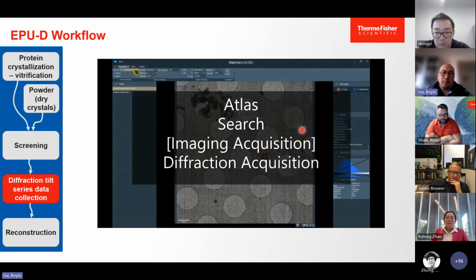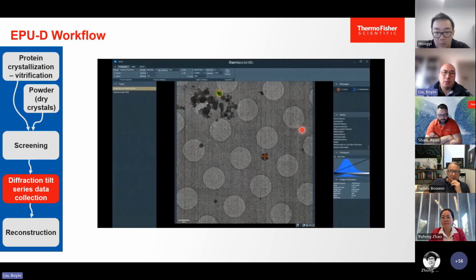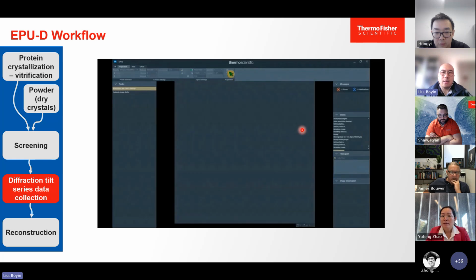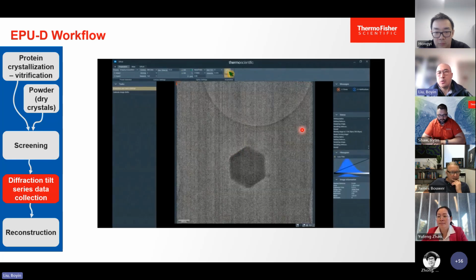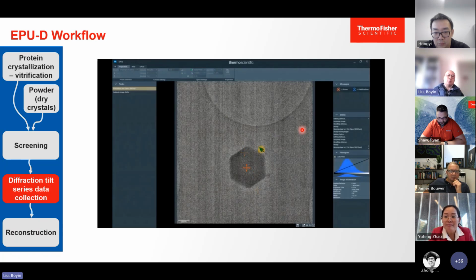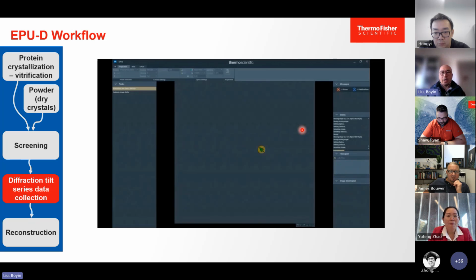And then go up, go one magnification up. Go to the next preset, the image acquisition preset. Usually we use 20,000 to 30,000 magnification, and then center the crystal, and then take a diffraction image for screening purpose.